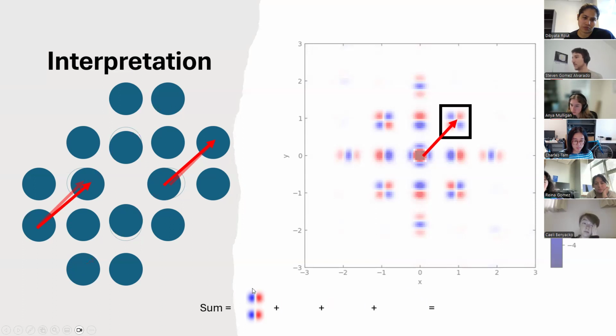And they're both going to constructively interfere with each other. So I'm going to plot those in the same term in this sum down here. Okay. I know this one looks like it's shifting to the left, but you've got to connect vectors at their tails, right? So this new vector is actually pointing a little bit more to the right. I was confused about that for about 30 minutes yesterday, so think about that. The other correlation is these pairs right here, and those are both moving upward. Again, this one is moving up, and this one, the new vector has also picked up an upward component. So those two are going to constructively interfere.